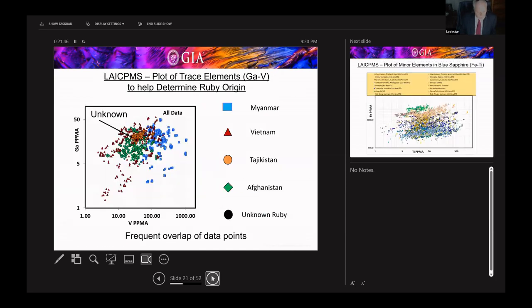What you end up with from that type of procedure is a plot, such as this one, which is vanadium on the horizontal axis and gallium on the vertical axis. Again, these are data points in terms of parts per million. What you're trying to do is compare your unknown, which is the black circle with the red edge, against known samples, which are shown in the various colors. Known other rubies, in this case from other countries, and you're comparing your unknown stone from your client.